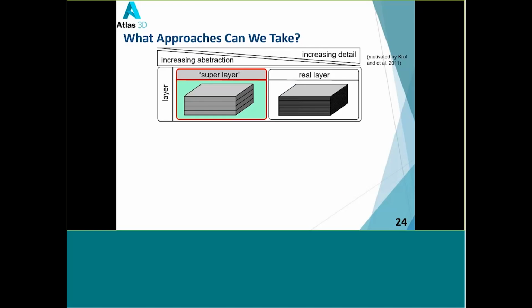So what approaches can we take to model the AM process? We can model the whole process with different details. For example, when we model each layer, we can model the real layer, which is about 30 or 40 microns thick. And we can also model a thick layer. I call it a super layer here. So each super layer represents multiple real layers.